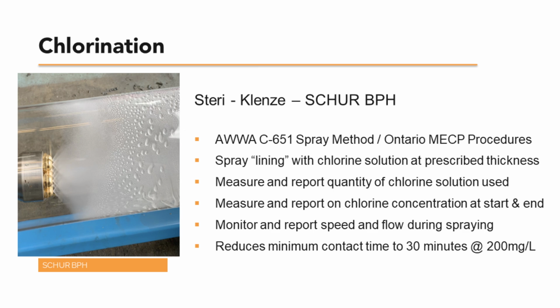The Steri-Klenze system emulates a spray-in-place lining rig, only the inside of the pipe is coated to a prescribed thickness with chlorine solution. Because pump rates and winch speeds are automated, a uniform thickness of chlorine solution can be applied quickly and with consistency. Chlorine concentrations may be recorded from day tanks before and after spraying the pipe to confirm concentrations meet standard requirements. Flow and speed may also be used to verify coating thickness.